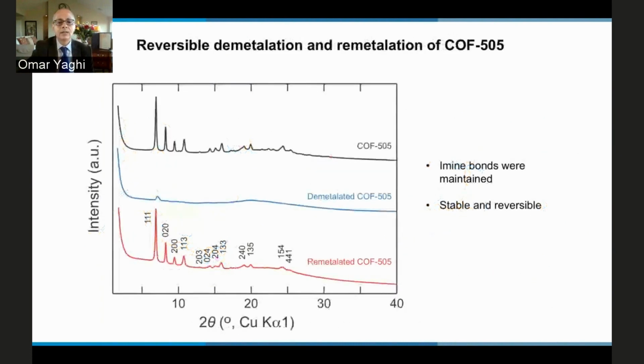This is the X-ray powder diffraction of the metallated. This is the demetallated. Obviously, you lose crystallinity, but you don't lose the structure. So the material is not amorphous, it's not crystalline. And you remetallate to regain the original structure, which means that the threads are still interlaced and have not gotten unzipped.